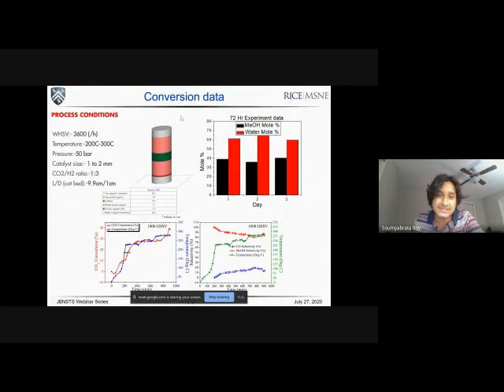And this is a schematic of a reactor. The green region is where we put the catalyst, and the pink is where we put some other inert solid materials so that the layer of catalyst can be balanced. Then we pass the CO2 gas through this reactor at a certain velocity, expressed as WHSV, weight hourly space velocity. We pass about 3600 ml per hour of gas, and the temperature is optimized between 200 and 300. We operate at 50 bar of pressure, and we have different catalyst sizes.